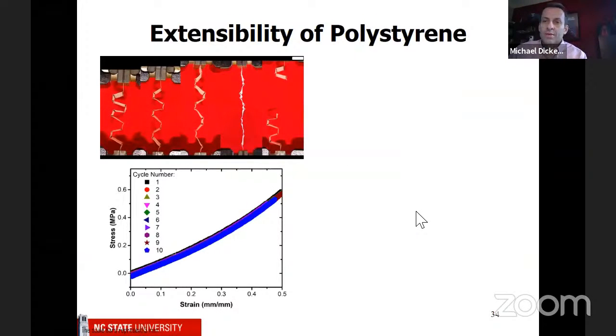Okay, so let me show you the stretchable part. These are the corrugations, and as you might imagine, we make this using light, by shining light on the sample, and it's stretchable. You can see you can stretch it pretty far, and eventually it will break. But when we do this, you can see a strain of 0.5 means about 50% of its original length. It's a polymer like this pen. It's hard. If I pull this, I cannot stretch it. But because of the geometry here, we're able to actually stretch it.